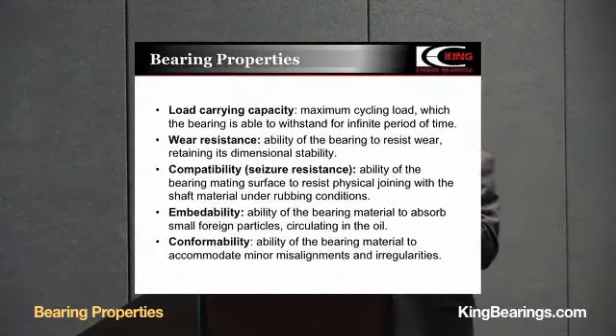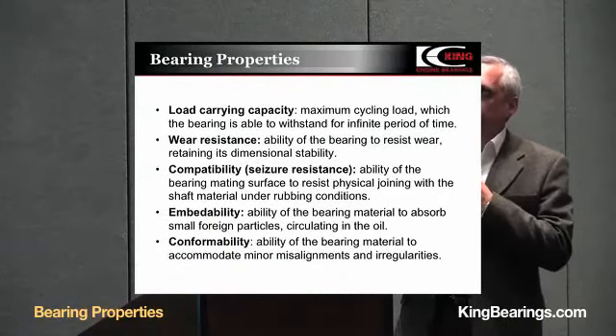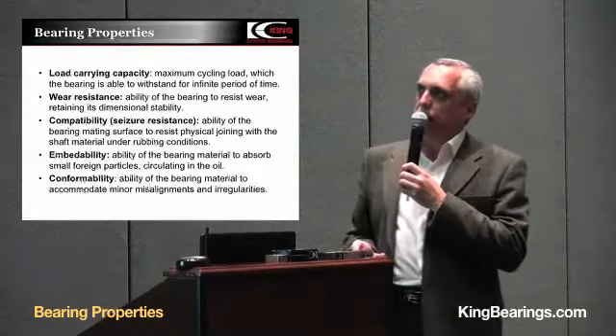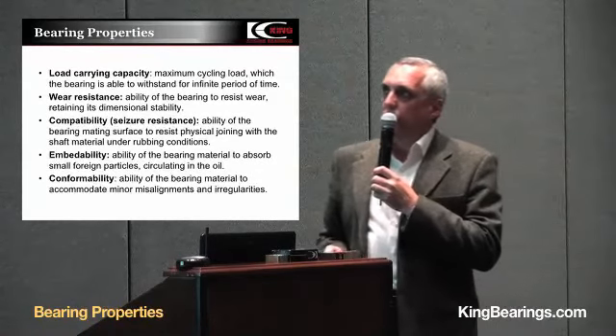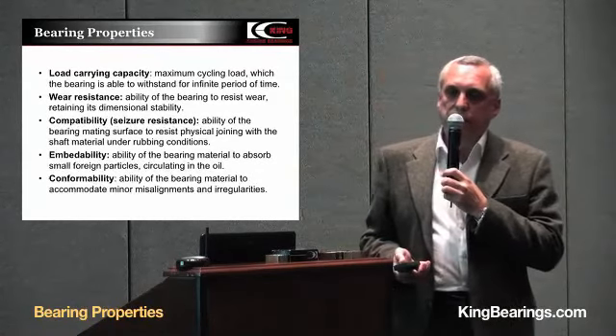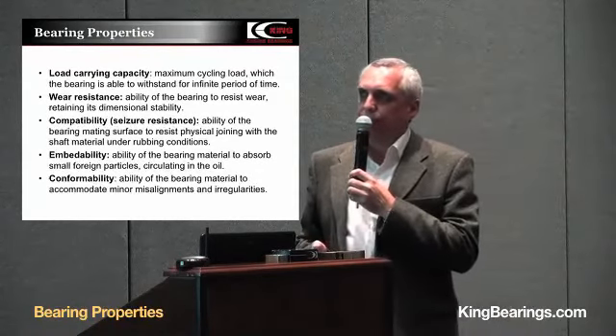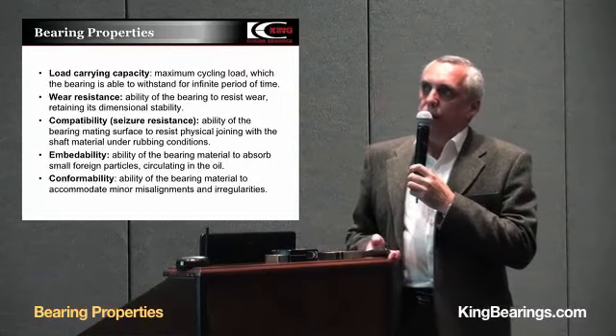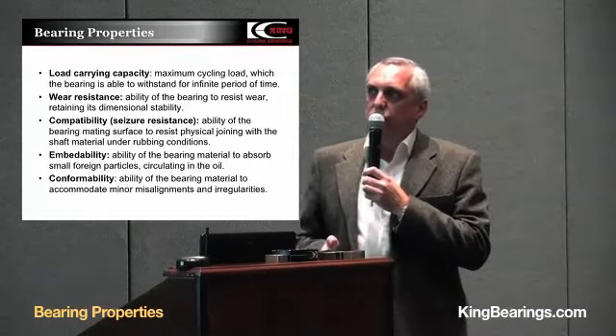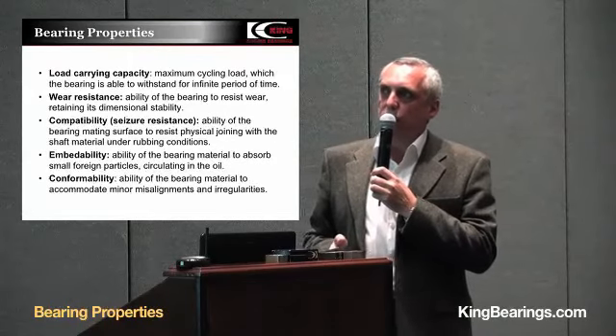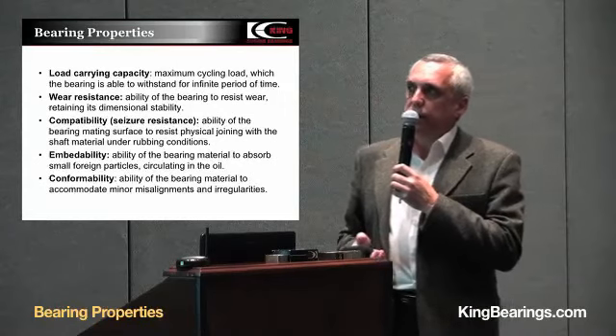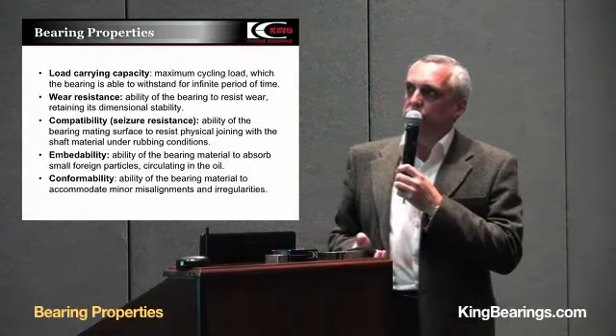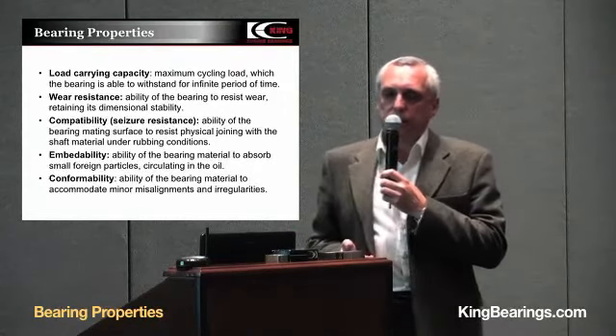Now the main bearing properties. First of all, load carrying capacity. Load carrying capacity is the maximum cycling load which the bearing is able to withstand without failure for a long period of time. This is maybe the most important characteristic of bearing materials. The second is wear resistance — the ability of the bearing to resist wear and to retain its dimensions.